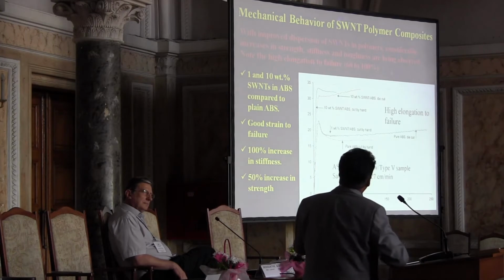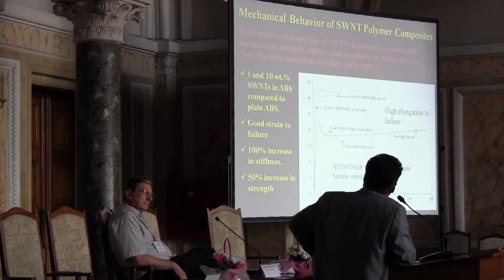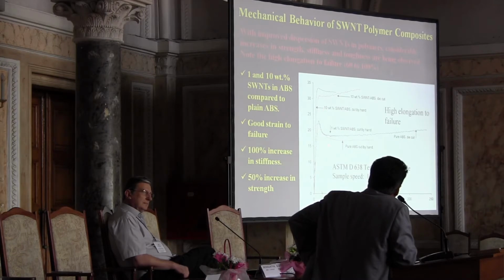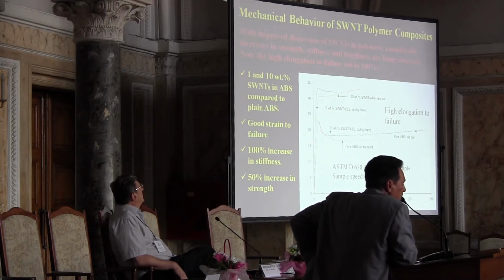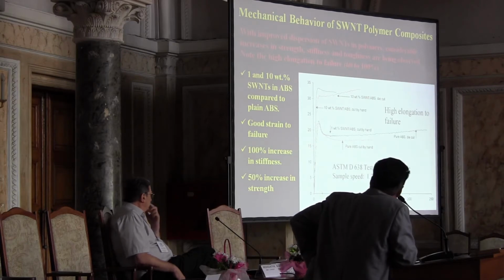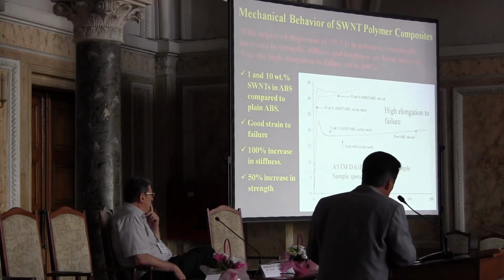So moving into structural results, you are seeing the incorporation of carbon nanotubes in ABS. And what you are seeing in here is that with a 10% load, you increase the strength on the order of 50%. So the strength is given by these peaks in here. And the stiffness of this composite, which is the slope of that curve, is increased 100%.